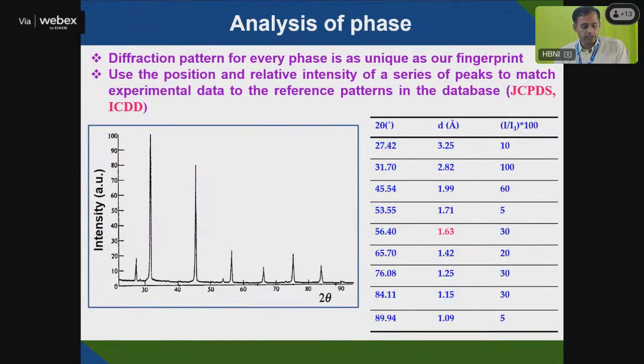So how do you analyze? Once you get a diffraction pattern from XRD, the next step is to identify it. I have given a spectrum here. You can see that it's intensity versus 2 theta, and I have given the peak positions at 27, 31, 45 and around 56. So all peaks have been identified.